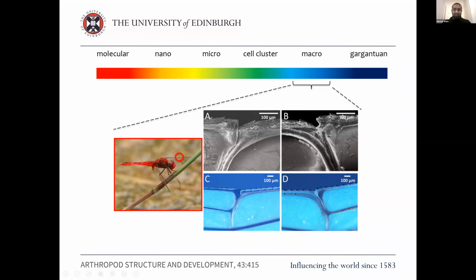analyzed the wings optically using SEM, light microscopy, and also confocal microscopy. We analyzed the structures and found that in the joints of the wings, there was a hard, soft, hard segmented structure. And the soft part was resilin, essentially. It's a very rubbery protein biopolymer that these dragonflies produce. It seems that the resilin deforms a lot during flight, and basically stores a lot of that energy and then releases it.